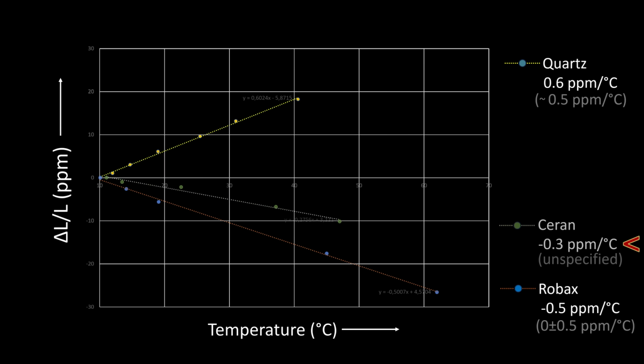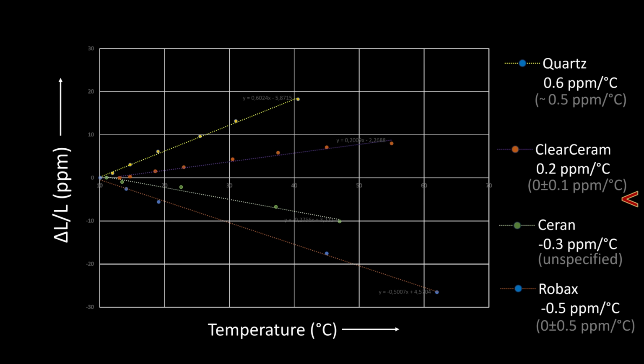Next is Ceran, which also has a negative CTE of minus 0.3 ppm. The last measurement is on clear ceram, which resulted in a value of plus 0.2 ppm per degree Celsius, the lowest value of them all in the absolute sense. And if we compare the latter value with the value specified in the datasheet, plus 0.2 ppm is outside of the tolerance range of plus or minus 0.1 ppm, but I guess that here we are actually hitting the accuracy limit of the setup, which I think is in the order of plus or minus 0.1 ppm per degree.